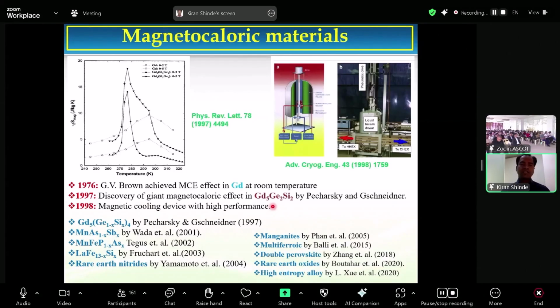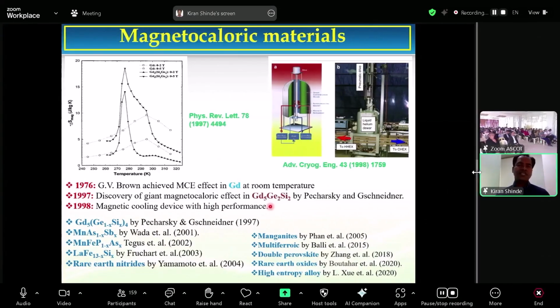And these rare earth nitrides or rare earth oxides can be useful at the cryogenic temperature region, like, as I said, liquefaction of hydrogen, as hydrogen gets into the liquid state at 20 Kelvin. So this kind of rare earth nitrides and oxides show the magnetocaloric effect around 20 Kelvin. So they were discovered in 2004.